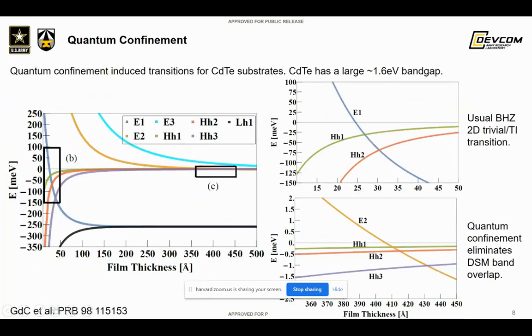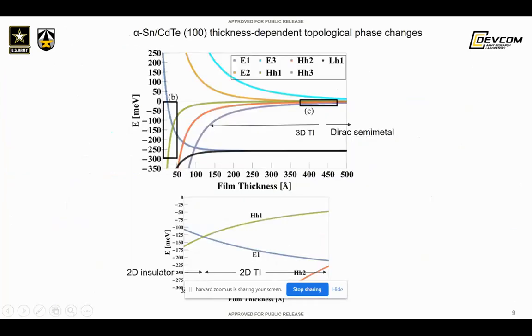So the next slide shows some more details in this region. I'll just emphasize that in this material, you can see more details as you go from a 2D trivial to a topological insulator transition. A little more detail is shown there. The next slide shows, in essence, the same thing, except that I point out here that you go to a 2D insulator below this thickness. So there's a critical thickness at which all topological material characteristics vanish. You go through the final inversion, you uninvert the final bands, and you end up with a 2D insulator as you go to very small thickness. This is for the case of cadmium telluride substrates with a thickness of the order of 25 angstroms or so.